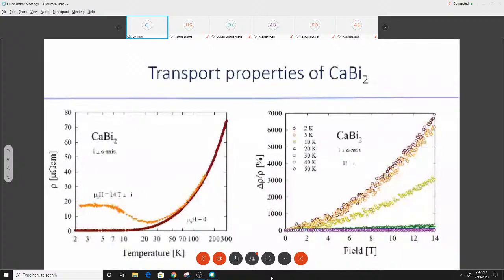sample. On the right side, we show the magnetoresistance plot, and it shows a high magnetoresistance, similar to WTe2 and GdSb type materials. The magnetoresistance shows a non-saturating value, and it reaches around 7,000 percent at 2 Kelvin. This indicates this could be an interesting material, or it may have some topological origin.